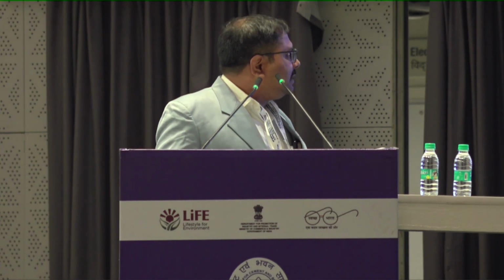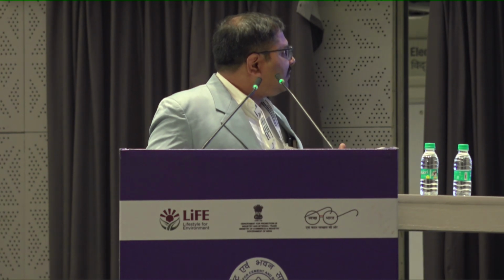So we all know the loss on ignition in LC3 is due to the limestone content used. Conversion factor is just double. We have carried out the workability test and compared with PPC. Out of this test, it has been arrived that admixture content is approximately increased by 40% to retain the same workability.